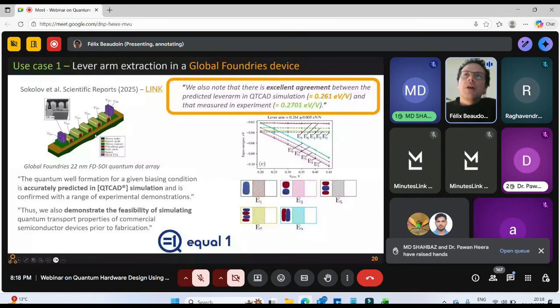They measured the so-called lever arm. So they computed with QTCAD all of the energy levels of the quantum dots in this array and found how they behave as a function of gate biases. So you have an electrostatic gate bias that controls the energy levels. And this lever arm tells you by how many electron volts the energy level of the quantum dot shifts when you apply 1 volt on a given gate. So this tells you how much control you have on your quantum dots electrostatically. So this was done using QTCAD.